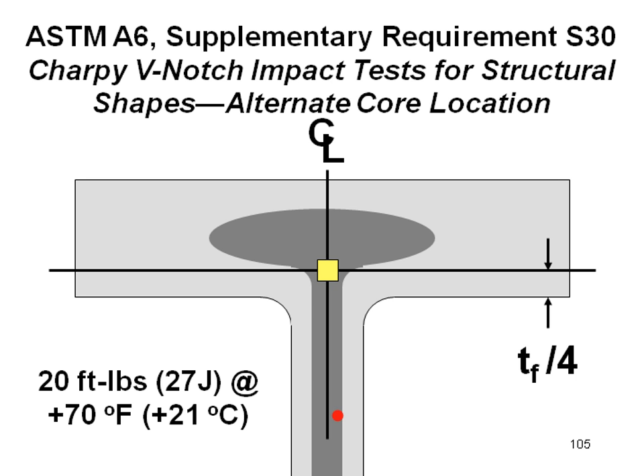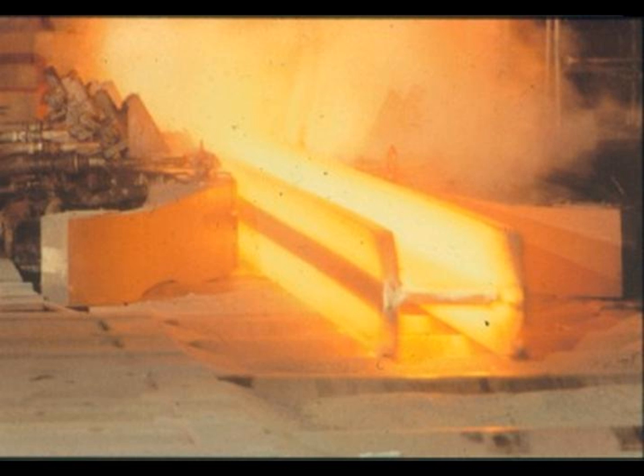Now, of course, that's a more complicated area to extract steel from, but that became the required test. Eventually, that became a standard ASTM test. That's Supplement 30, which is to the ASTM A6 specification. And out of that region, there was a requirement that the steel exhibit at least 20 foot-pounds at 70 degrees F.